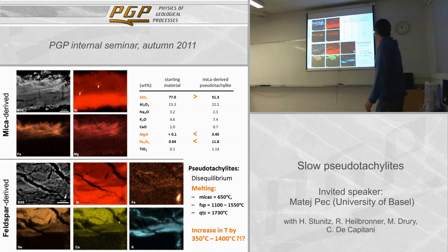So we can see that we melt micas, we melt feldspars, we melt also quartz, and this is typically interpreted, because the pseudotachylites should form in the order of seconds, that it's the single phase melting actually that matters. So if people observe molten quartz clasts, they infer temperatures on the order of 1700 degrees, which are the single point melting temperatures for quartz.